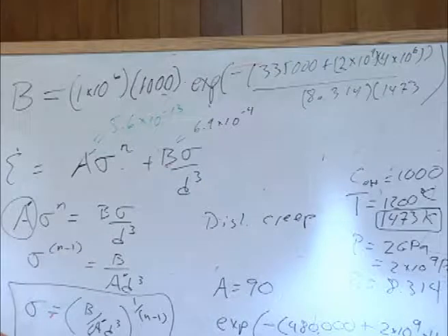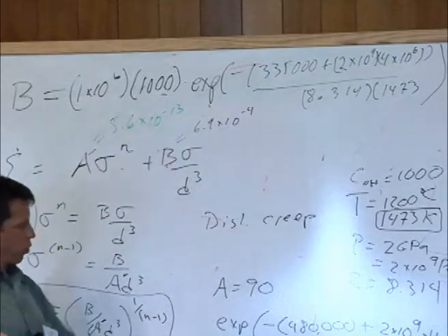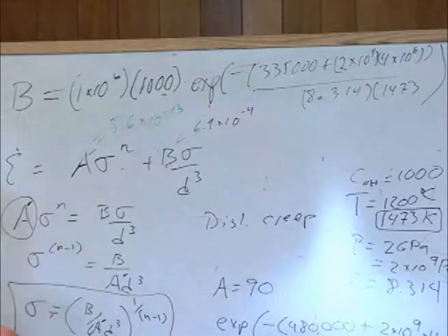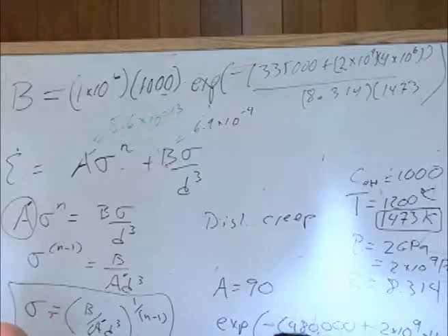So this is the water. This is the water content. All right. So if you made a plot of strain rate as a function of water content, and you fit all the data, you get that it's almost linear, but the data are better fit with the exponent being a little bit bigger than 1. Okay.